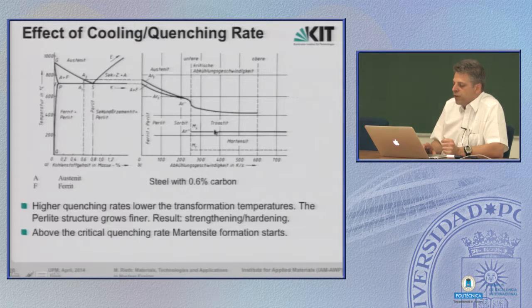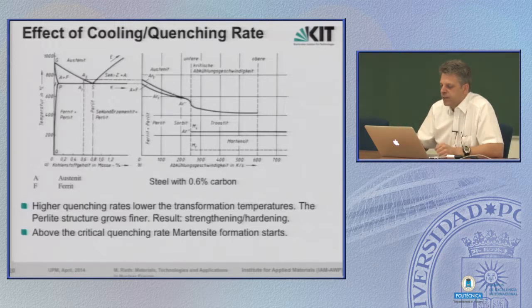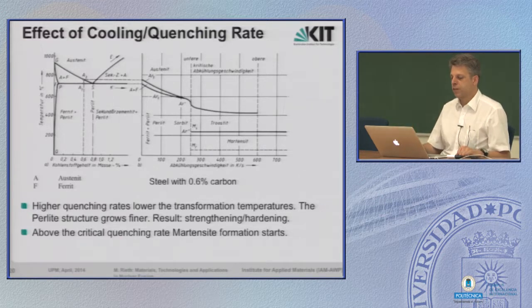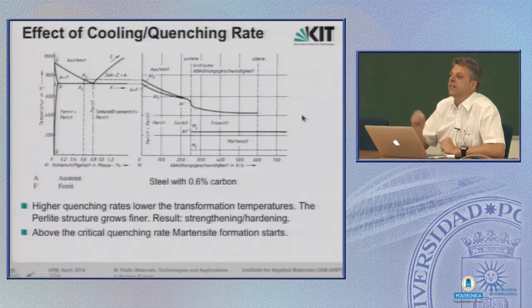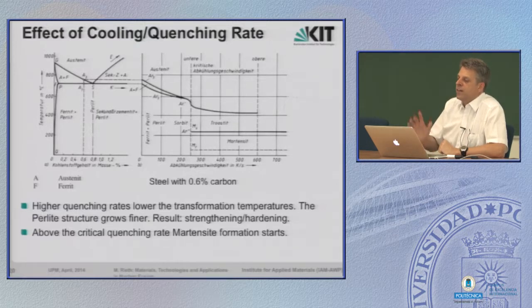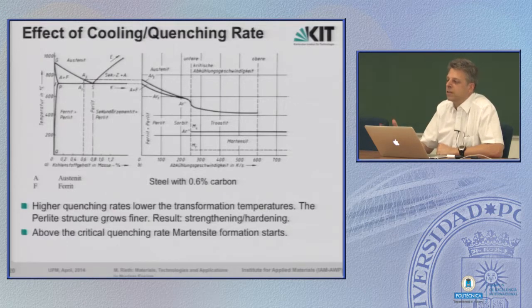So we have produced here pearlite, a very fine pearlite structure, but still with further cooling down we produce a martensite phase. Then if you increase the cooling rate further and further, there is another limit, 600 Kelvin per second. If we go above this level, then there is no formation of pearlite anymore, there is only martensite formation. And this phenomenon is used in a very specific way for a broad variety of steels, for example this 9% chromium steel, as we see later. But it also works for a simple iron carbon steel, that's a mild steel.